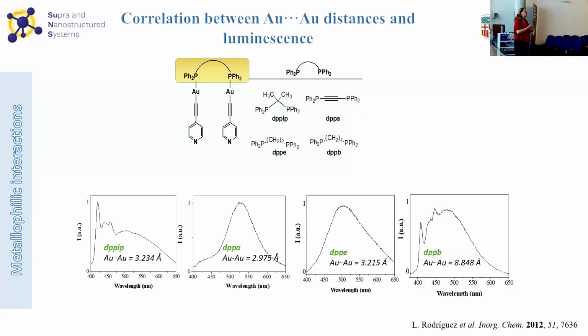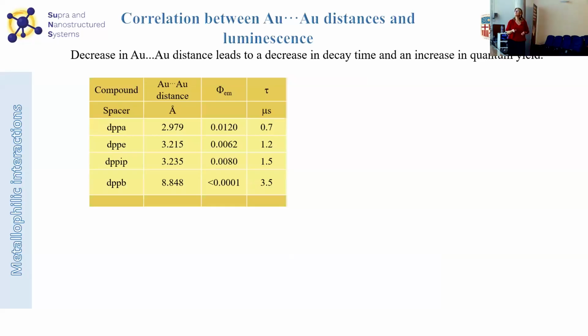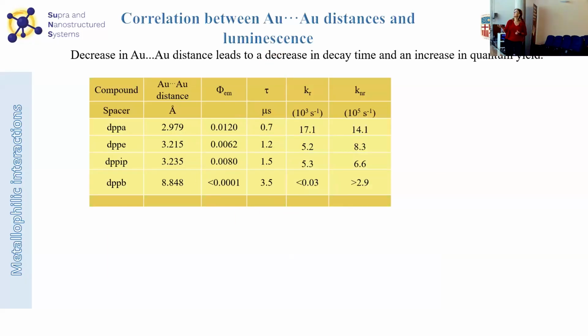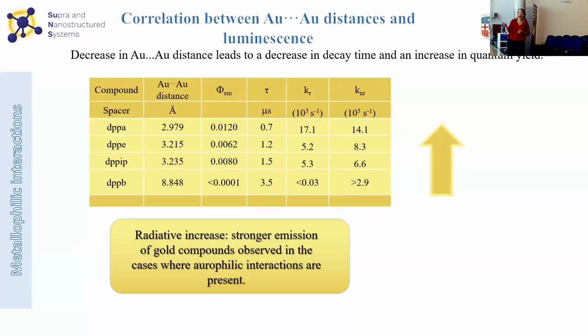So we cannot see a direct correlation between the presence of a broadening band and the presence or absence of aurophilic interactions. But what we could see is that there is a direct correlation with the radiative processes. If we measure the emission quantum yields and the lifetimes, we can calculate the radiative and non-radiative rate constants. With this, we can observe that the radiative rate constant increases 2 orders of magnitude when we go from near 9 angstroms to near 3 angstroms, while the non-radiative rate constant varies much less. So the direct correlation is that the aurophilic contacts may favor this radiative emission.